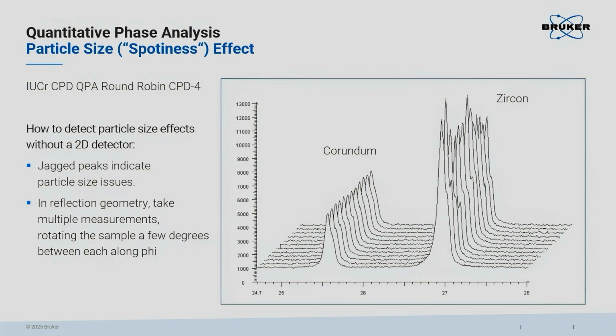If you have a sample with a spottiness problem, it will show up also in your powder patterns. It is always characterized by such jagged peaks. This is not to be confused with counting statistics. You can see that the counting statistics is small. So this is not just counting statistics, and it cannot be, because if that was counting statistics, then the peaks of corundum should be affected equally.